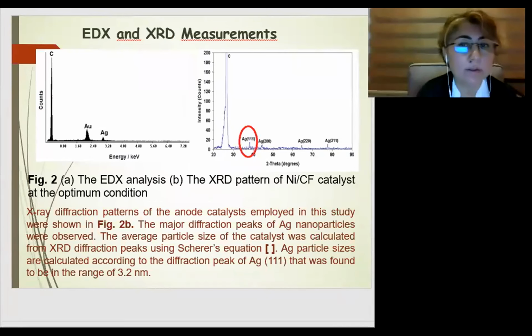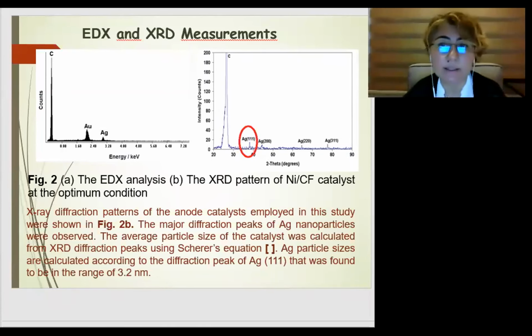Here in figure 2A and B. Figure 2A, the first one, displays the EDX analysis that confirmed the presence of silver with high intensity. The appearance of the carbon peak was the result of the activated carbon on which silver nanoparticles were deposited. The gold peak at around 2 kiloelectronvolts results from the grid used for the analysis. The EDX analysis has shown strong evidence of homogeneously dispersed silver nanocrystals at the optimum conditions.